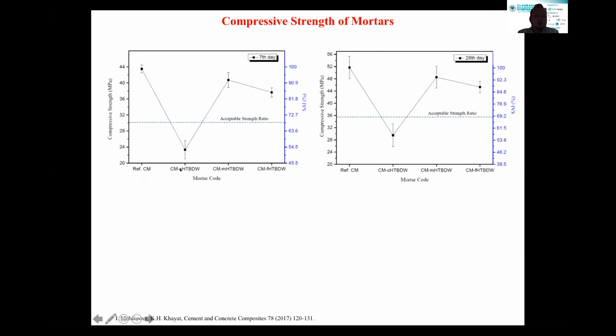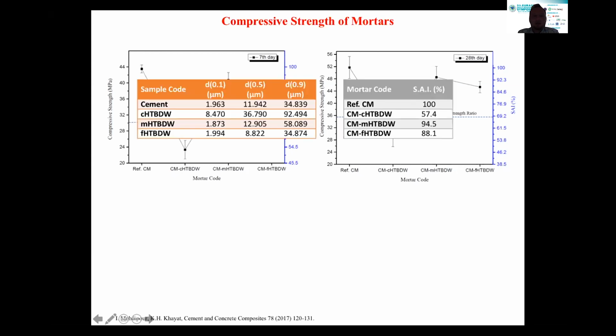So you can see now the compressive strength values for the 7th aging day and 28th aging day. After the addition of the coarse powder, we had quite a loss in the compressive strength, but for the other medium and fine powders, we got strength values in an acceptable strength ratio, and with the increasing aging time, the strength values increased a bit. Briefly, the particle size distribution affects the strength values. It is the strength activity index.